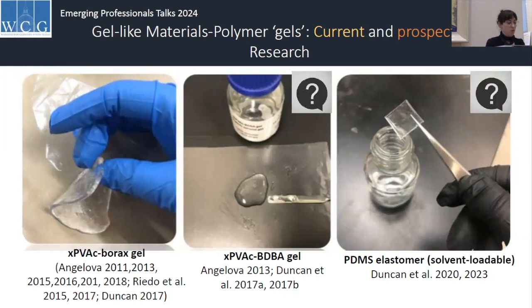So what I've primarily been looking at are polyvinyl alcohol borax gels, but I'm also looking at polyvinyl alcohol gels that will be cross-linked with benzene 1,4-diboronic acid, that's BDBA. They have two distinct advantages. The borax gels are rigid and flexible, they conform fully to surfaces, they adhere to vertical and high relief surfaces, they peel straight from the surface, and they self-heal so you can remold and reshape them. They constrain large percentages of organic solvents and small percentages of chelating solutions, they have a very slow controlled diffusion cleaning action, and they also have no demonstrable residues.